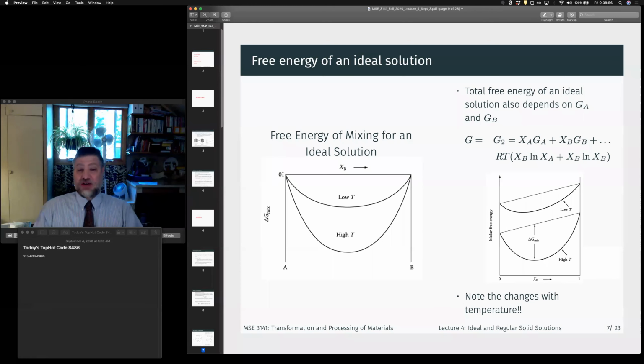That's not saying the change in Gibbs free energy is infinite. It's the slope, right? So the slope has to be infinite, right? So essentially that tells you that you always have a tiny, tiny little bit of solubility from the change in configurational entropy. It might be really small if the enthalpy term is large, right? So that's why oil and water are never going to mix, right? The enthalpy is just, the energetics are completely unfavorable. But you do get a tiny little bit dissolved because of this entropy change and the fact that this slope is asymptotically infinite.